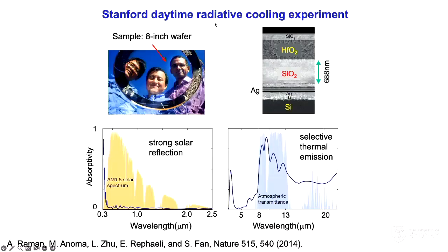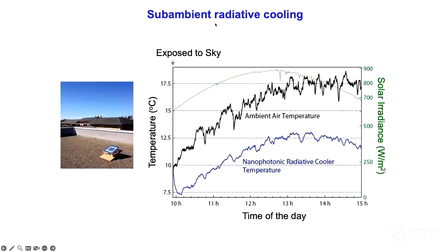On the long wavelength side, in the wavelength range of 8 to 13 micron, one sees an emissivity peak. On the other hand, in the solar wavelength range, it behaves as a very good mirror, as we show in this image. We then brought the sample to the roof of our electrical engineering building. Remarkably, we had a very nice flat roof for this kind of experiment. And on the right are some of the experimental data.